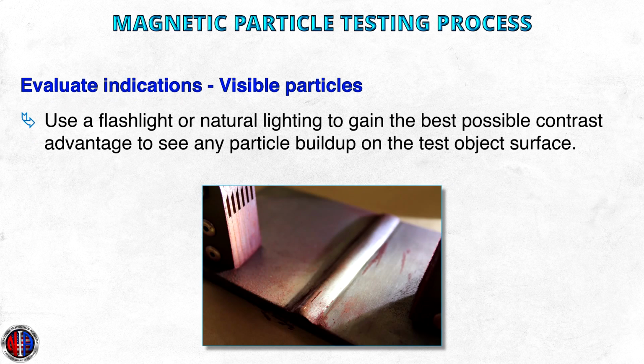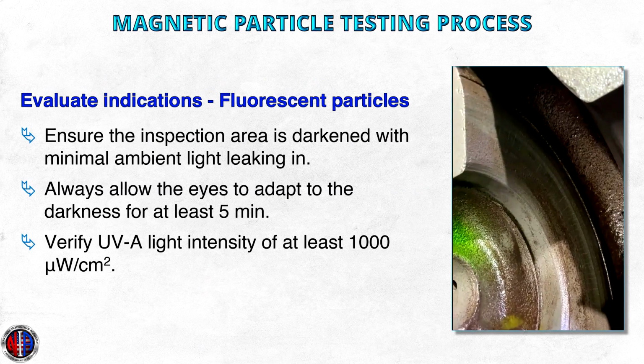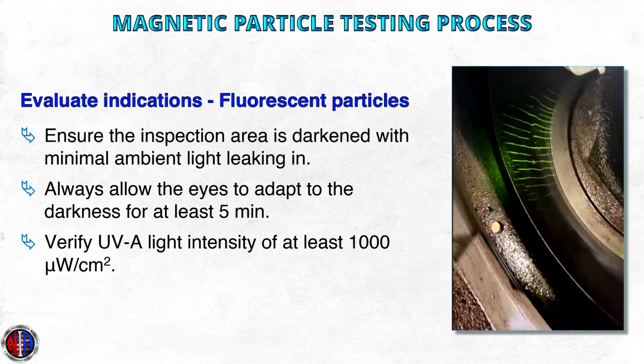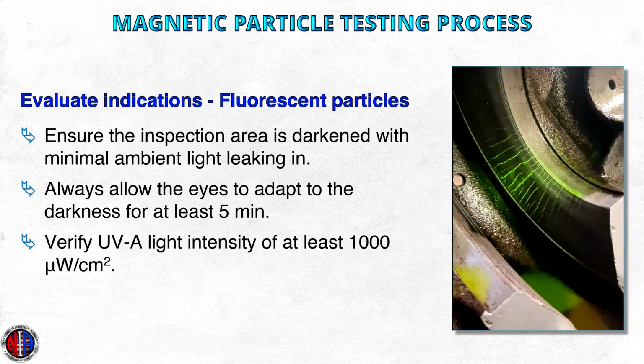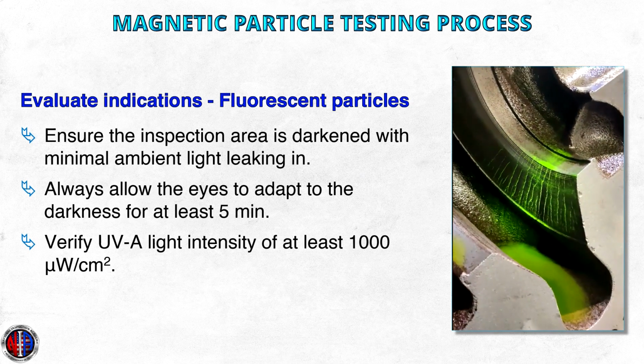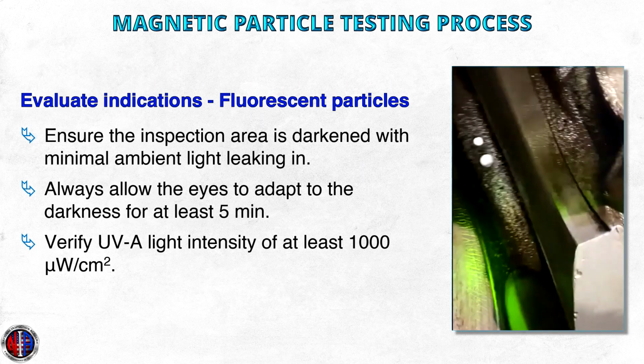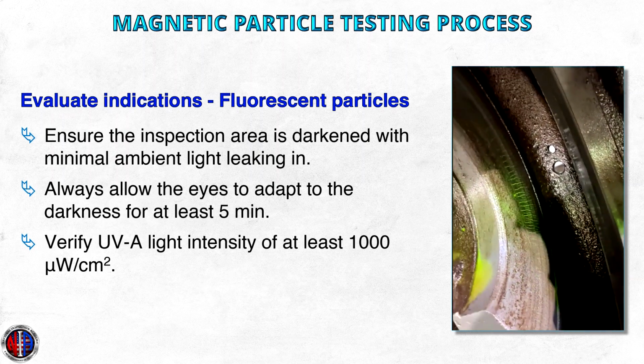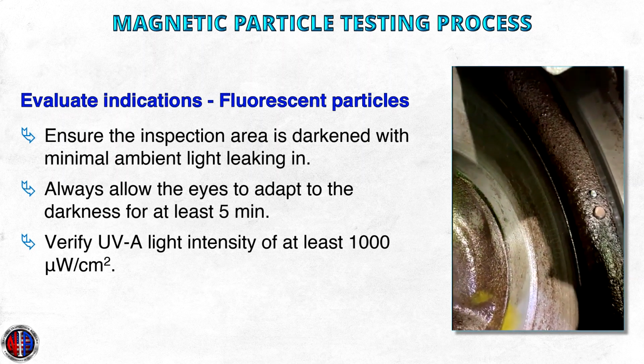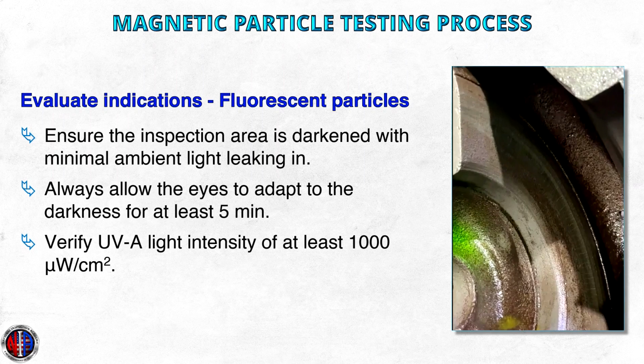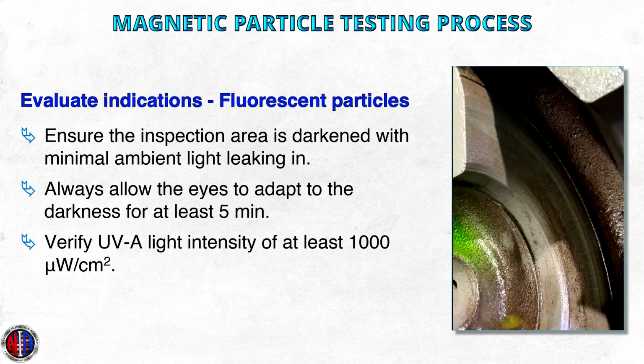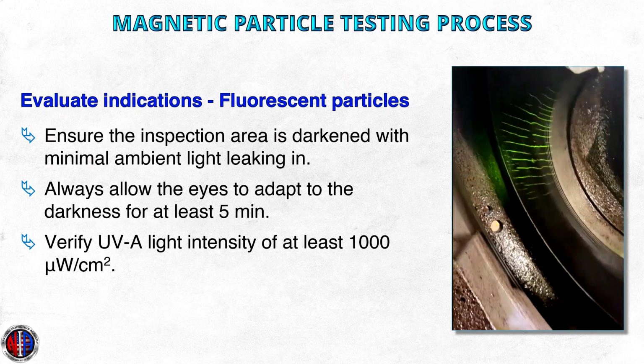Visible particles. Use a flashlight or natural lighting to gain the best possible contrast advantage to see any particle buildup on the test object surface. Fluorescent particles. Ensure the inspection area is darkened with minimal ambient light leaking in. Optimum darkness is less than 2 foot candles or 20 lux of ambient light. Always allow the eyes to adapt to the darkness for at least 5 minutes. Verify UVA light intensity of at least 1000 microwatts per square centimeter.